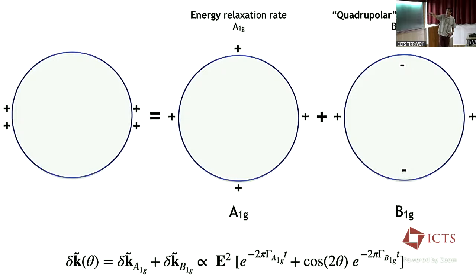Now, this is a state of finite energy, right, where we've excited everywhere around the Fermi energy. And for it to relax, the only things that will relax it are ones that take energy out of the electronic system. Scattering events which just reorganize the electron distribution function, Umklapp scattering, if you will, or electrons scattering off impurities, don't do anything to relax energy. One would expect that they will relax at different rates, because the conservation processes are different for both.